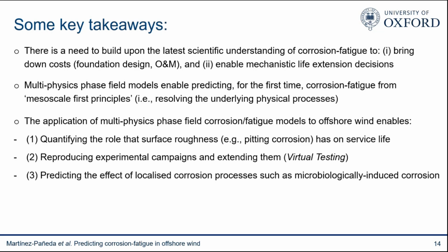In this FlexFund project, we were able to demonstrate the potential of these methods in 3 areas. One is quantifying the impact on service life of surface roughness, such as that resulting from pitting corrosion. 2 is conducting virtual experimental campaigns, bringing to the sector the virtual testing paradigm that has been so successful in other sectors such as automotive and aeronautics. And 3 is predicting localized corrosion processes, even if they're as complex as microbiologically induced corrosion.